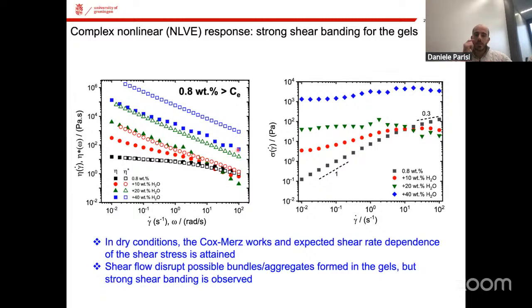So did I give more or less the idea of why this is important and why we care about the non-linear viscosity? Because the same thing can be witnessed if we look at the stress. This is the shear stress provided to the system, and this is the deformation rate. When the system is a liquid, you see that there is a slope of 1. If the deformation rate is below 5 or something like this, the sample is not feeling such a strong deformation. But then at some point when this nonlinear regime is attained, the slope becomes 0.3, which is something that we know from theory. So this is for very simple systems.